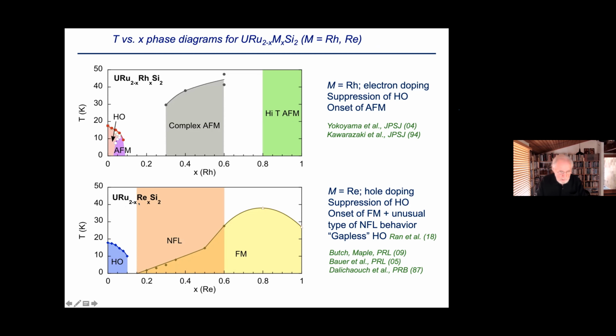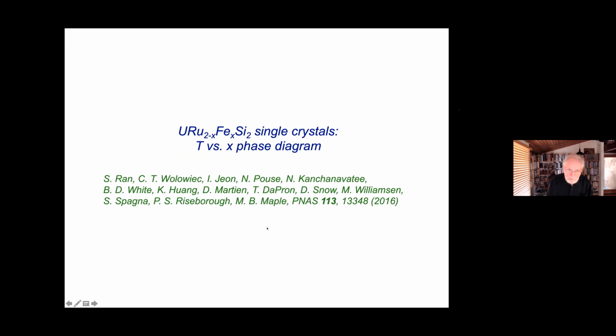And in this case, for rhenium substitutions, both of these types of substitutions suppress the hidden order. And here, again, nothing appears to happen, but the other interpretation is that the transitions become broadened, and so maybe you just can't see them in this region. And thermal expansion measurements and specific heat measurements indicate that the gap is decreasing as you go along this line. Okay, then you enter into this ferromagnetic region, and some very interesting non-Fermi liquid type features appear in this region right here. And so we've done a lot of work on this phase diagram over the years. Okay, so now coming to the iron substitutions, which is where this more recent thing we've been working on started.